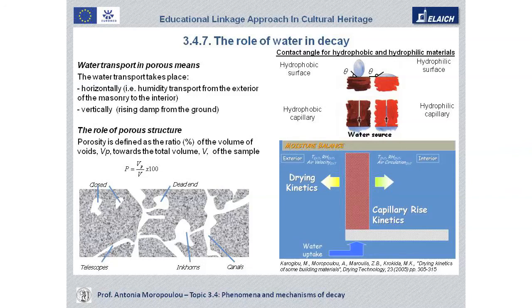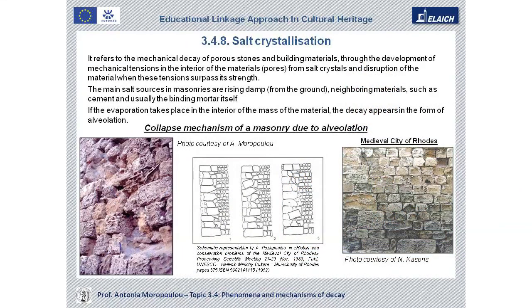Not only because it might alter, for instance, soluble stones, like the ones that are consisting of argillaceous minerals, but mainly because in the case of insoluble stones like the calcitic ones, it might, within the cycles of drying due to the evaporation of the environment, develop salt crystallization, which is deteriorating and damaging materials and structures.